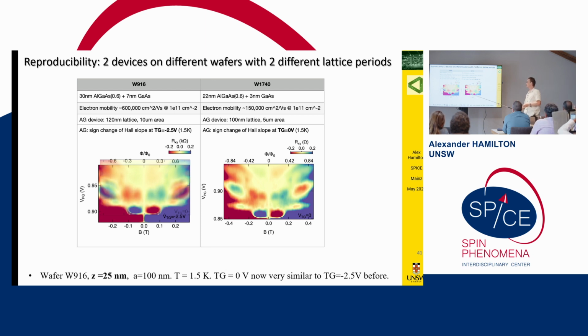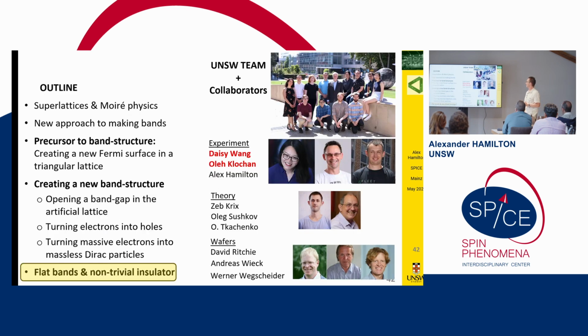And so we've measured something like 8 or 10 of these devices now, and all of them show the same behavior. All of them show the same band filling. It's really nice. So we've got a way of making artificial bands. We've demonstrated it with triangular lattices, but I'm sure we could demonstrate it with square lattices, Lieb lattices, any kind of lattice you want, as long as it's 2-dimensional. Could we make flat bands, and could we artificially create correlated states?